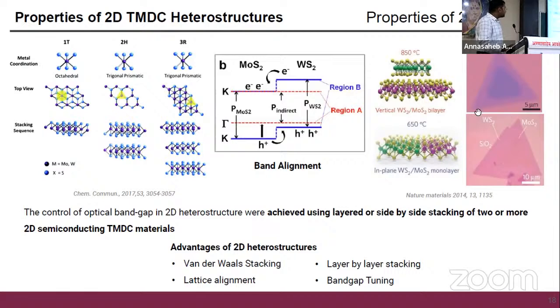Typically you can see two kinds of heterostructure formation. Here is a vertical heterostructure formation between MoS2 and WS2, where on top of each other there will be heterojunction formation. The band structure will show individual properties of MoS2 and WS2, as well as the heterojunction region. Here, in-plane or lateral heterostructure formation also takes place, where there will be a region with a heterojunction band gap in between the band gaps of the two other materials. Depending on this band gap, these materials can be used in many fields such as solar cells, photovoltaics, or photosensor applications.